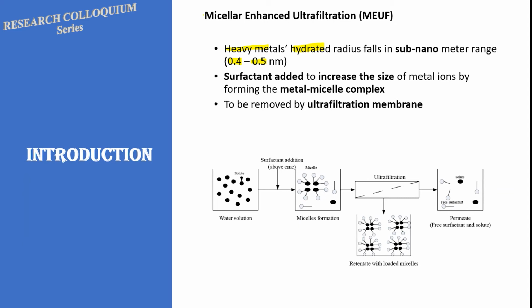Previously, we tried to use nanofiltration. Yes, it works fine with these heavy metals. Eventually, all the heavy metals could be rejected by more than 99% from the solutions. But at the same time, when we use nanofiltration, the pores of the membrane are very small, so we have to use a very high operating pressure, for example, pressure above 7 bars. In the meantime, it seems like a lot of energy will be consumed in nanofiltration.